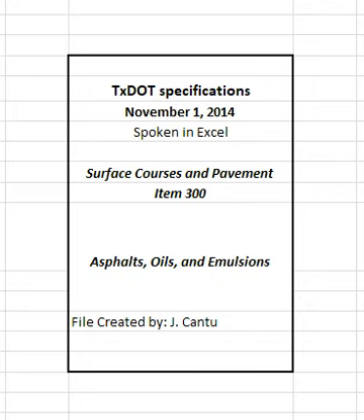Exception to T59, maintain sample at 300 degrees Fahrenheit until foaming ceases, then cool, and weigh. 2.7 Crumb rubber modifier. Crumb rubber modifier, CRM, consists of automobile and truck tires processed by ambient temperature grinding. CRM must be free from contaminants including fabric, metal, and mineral and other non-rubber substances. Free-flowing, and non-foaming when added to hot asphalt binder.